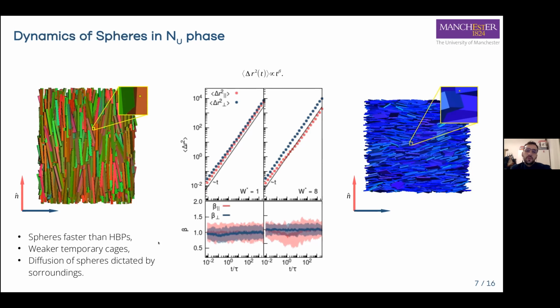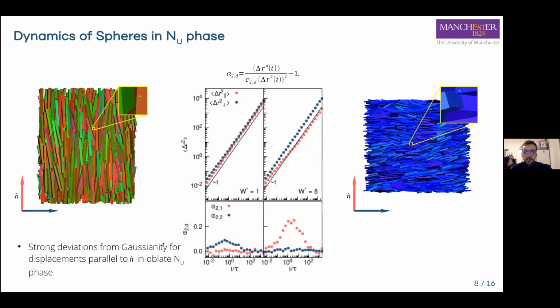And in this case, these spherical tracers are much smaller than the cuboids. So it seems that there is no presence of temporary caging effects, or they are much weaker than the ones that you observed for cuboids. And overall, since the particles are much smaller and the dynamics is defined by Brownian motion, they diffuse much faster than the cuboids.